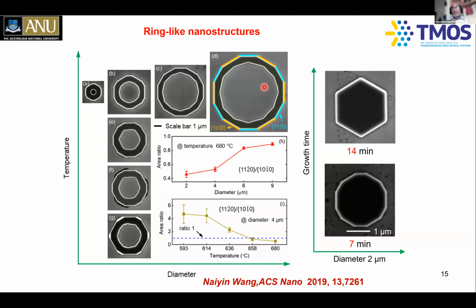So if you keep on growing, then it really gets filled up, and you can see the nanomembrane here again, which is in the horizontal direction, the vertical direction, which I've shown you earlier. And it finishes off, if you keep on growing, with these beautiful hexagonally faceted structures, again because of the low energy facets being 110 facets, which the crystals like to be in whenever you go.